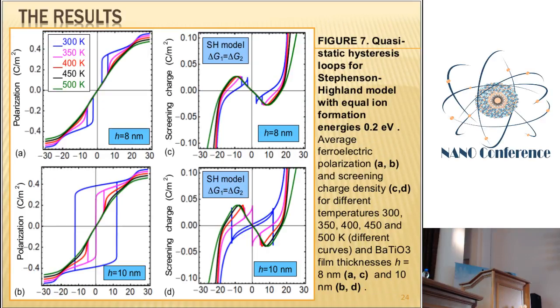Well, the situation with the Stephenson-Highland model is more pronounced. Here we can see a clear double hysteresis loop for a very thin film, 8 nanometers, below 10 nanometers. Our goal was to show how thin films can be ferroelectric with appropriate screening. And this double loop disappears with temperature increase.